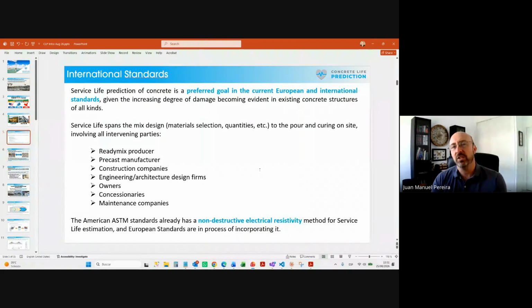Okay, detaching the strength from the durability, because we all know there is a relationship, but it is not a constant relationship through all the mixed designs and through all the different binders. Okay. So the initial reference was the ASTM standards for non-destructive electrical resistivity testing. Now there's, of course, also a European standard on that, and this is what we base our system on. Okay, the non-destructive test, which is electrical resistivity.